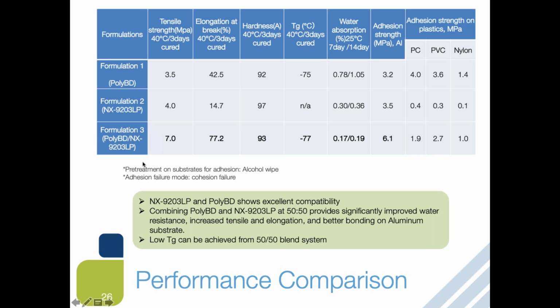As you can see, formulation 3, with 50% poly-BD and 50% 9203 LP, has shown increased tensile strength and better elongation in comparison to the other formulations. It also achieved a very low Tg, pretty much the same as poly-BD itself. And the water absorption data at 7 days and 14 days immersion shows much better water resistance performance, even better than poly-BD. We also showed excellent adhesion strength on the aluminum substrate here.